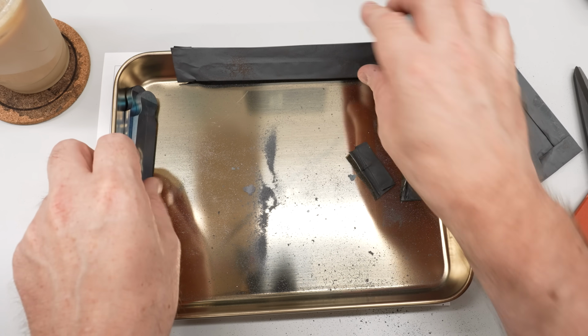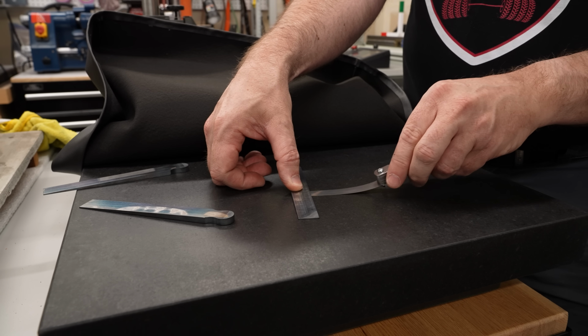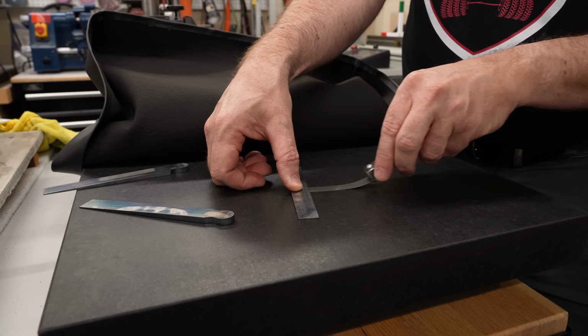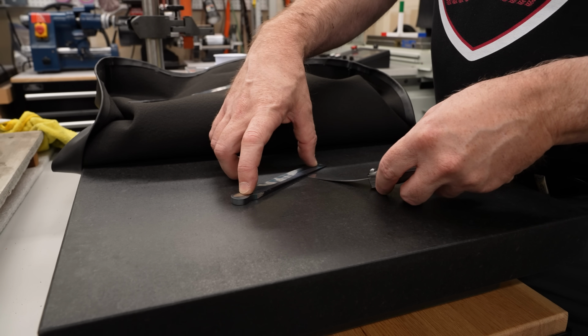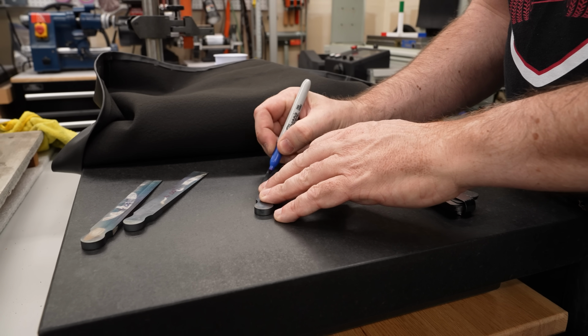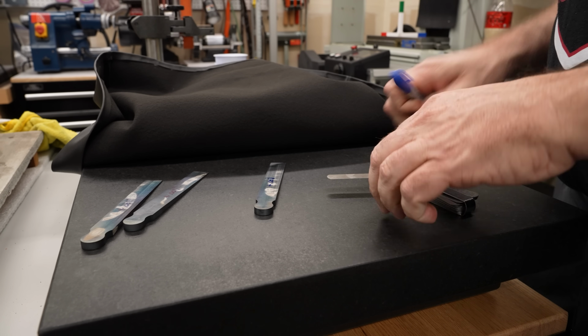The heat treating is definitely worth it if we want to make a durable tool that will last, but the multiple heating and cooling cycles take a lot of time. It definitely ended up being the most time-consuming part of the project. Inspecting the parts on the surface plate, they all came out bowed less than 9 thousandths of an inch. One of them was only 3 thousandths. That's less than the amount of material we still need to grind off to reach dimensions, so I don't think it's worth trying to straighten them first before grinding.